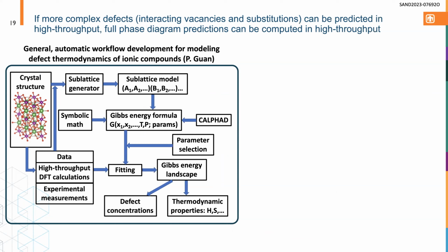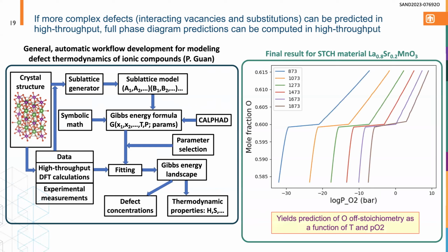So this is work done by a postdoc in our group, Pinwen. He's a thermodynamic modeling expert. He's developed this automated workflow. It's very complicated. I'm not going to go through all of it here, but this is basically a way to take a crystal structure, DFT calculations, and experimental data and turn that into a phase diagram. So if you click next, the output of that whole workflow is essentially the ability to predict the oxygen off-stoichiometry in a material as a function of the temperature and oxygen partial pressure. So you say, I operate my reactor between these two conditions. This is the amount of oxygen we remove from the lattice, and therefore, how much hydrogen we can produce in this thermochemical cycle.